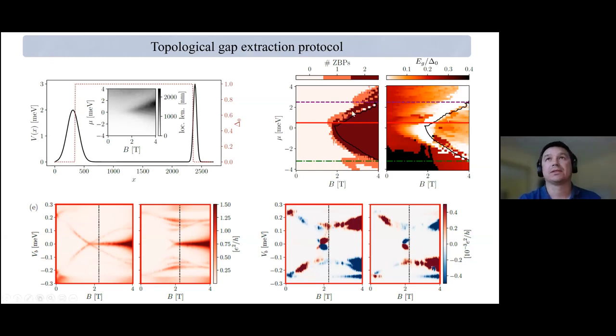But now let's consider the other 2 regimes. In this lower regime, you can see that the visibility for the phase transition is dropping. And the reason for that is that localization length becomes very, very short, and eventually becomes shorter than even the topological coherence length. So in this regime, we don't expect to see a topological phase based on our understanding of disordered superconducting phases.